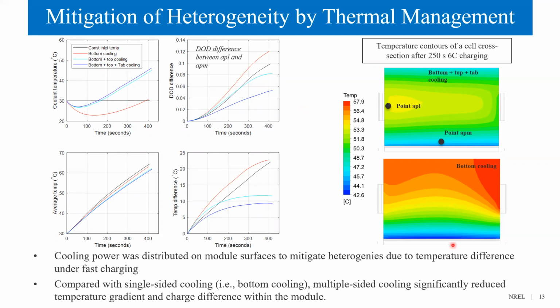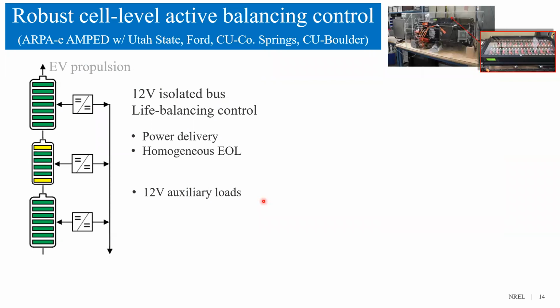Compared with bottom cooling, bottom and top cooling reduced the temperature and the DOD difference within the module by about 10 degrees Celsius and 4% respectively at the end of 6C fast charging. With additional tab cooling, the DOD difference was further reduced by 3%.